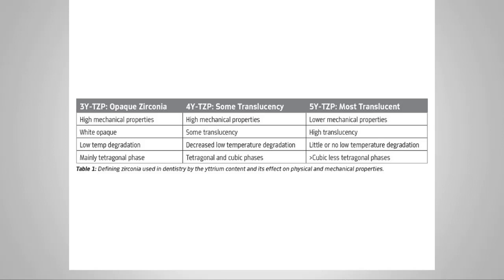So on the left of the slide, this is going to be 3 molar percentage yttrium stabilized zirconia. All that means is how much yttrium is going to be in the zirconia. And if you read the little table note, it talks about how the yttrium content affects the physical and mechanical properties of zirconia. So originally all we had was the 3 molar yttrium stabilized zirconia. So that was certainly the first zirconias we had. As you see, it says underneath them they're very white and opaque. And you also see that it has very high mechanical properties. So this is the zirconia that most of us think about.